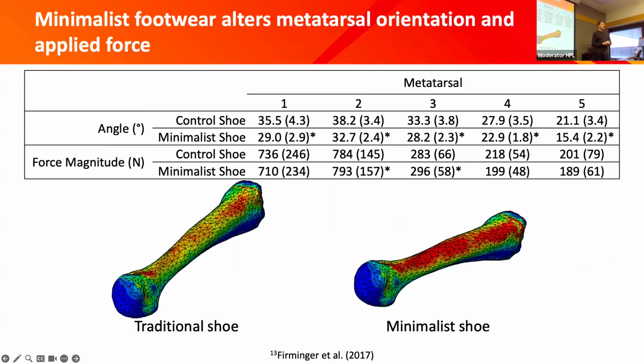And what was driving that? Well, if we look specifically at the inputs into our model that we're using to calculate strain, we have the angle of the metatarsal and the force applied to that metatarsal. If we zero in on metatarsals 2 and 3, we can see that in the control shoe, or a regular shoe, the angle was significantly higher than in the minimalist shoe. To say that colloquially, the metatarsal was staying flatter in that minimalist shoe at the time point of peak strain. So that was causing this increase in strain, paired with a change in force magnitude.